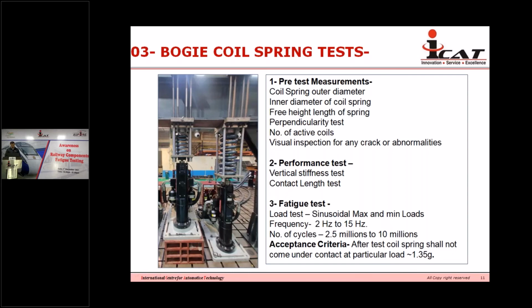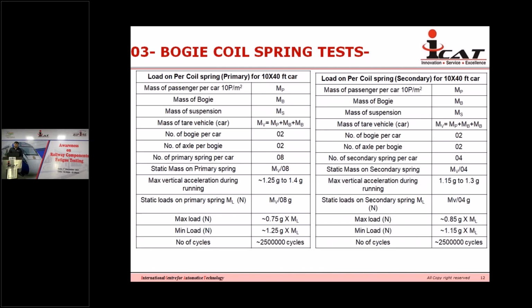So we can conduct up to 25 lakh cycles and more than that, depending on the customer's requirement. The acceptance criteria related to this test is, after testing of the complete cycle, we need to check the contact of these spring coils. There should not be any contact between these coils at a particular static load or higher loads. It is generally 1.35 G of the static loads which is coming on the spring.